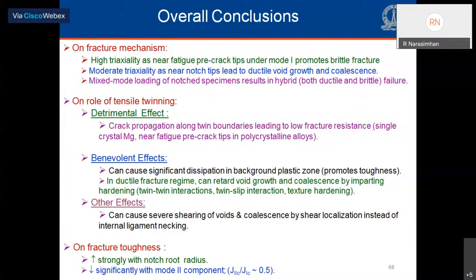And in the ductile fracture regime, as we saw from the unit cell simulations, it can retard the void growth and coalescence. The reason being that it triggers various hardening mechanisms, like the twin-twin intersections, which we saw in our EBSD images, and twin-slip interactions. Twin boundaries act as impediments to dislocation slip, and there is also texture hardening imparted by lattice rotation. So all this manifests in terms of high hardening and retardation in void growth.